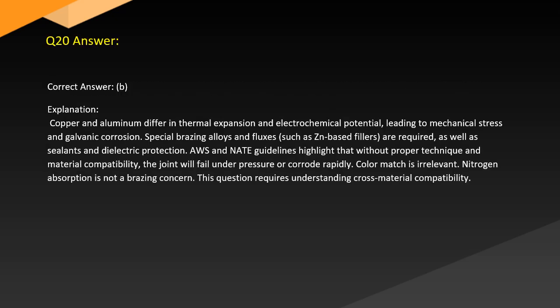Answer. Correct answer: B. Explanation. Copper and aluminum differ in thermal expansion and electrochemical potential, leading to mechanical stress and galvanic corrosion. Special brazing alloys and fluxes, such as zinc-based fillers, are required, as well as sealants and dielectric protection. AWS and NATE guidelines highlight that without proper technique and material compatibility, the joint will fail under pressure or corrode rapidly. Color match is irrelevant. Nitrogen absorption is not a brazing concern. This question requires understanding cross-material compatibility.